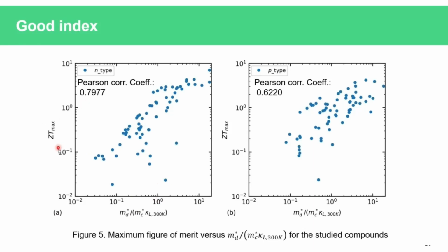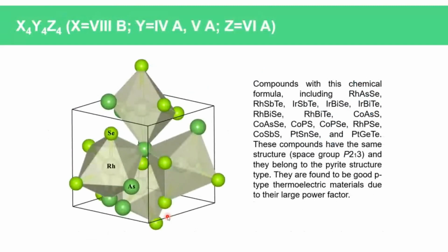Again, there is a clear trend that the higher this variable, the higher the maximum figure of merit. The Pearson correlation coefficient for N-type is 0.7977, while that is 0.62 for P-type. Although such a correlation coefficient is still a bit low, we believe using these three parameters, or the index most relevant with them, as input in a machine learning model could result in a high accuracy prediction of the figure of merit. This is actually the next step we want to do.